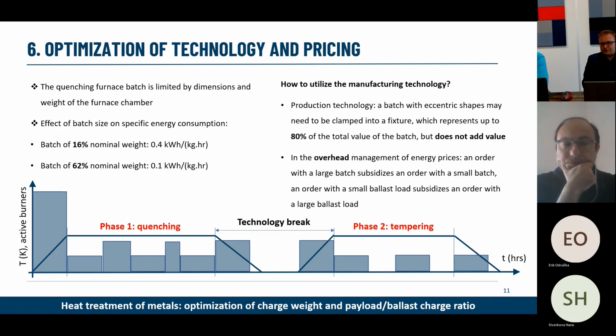So another interesting aspect in that company was that some of the batches were a bit of an eccentric shape. You might have some chunky piece of steel that you just plug in and you don't worry about it changing its shape. But imagine that you have, for instance, a ring that has a big diameter, and you need to plug it into that thermal processing device, and you need to use a jig so that you fix it in a position so that it doesn't twist. Some of these eccentric shapes can easily twist, and you would basically have to scrap it afterwards because you cannot maintain the dimensional tolerances.